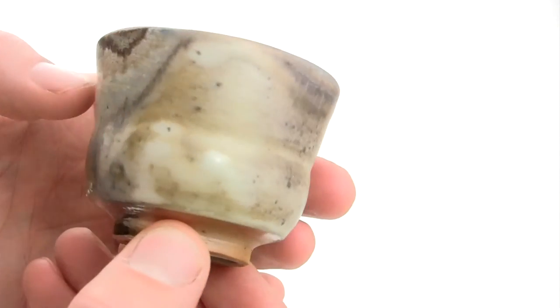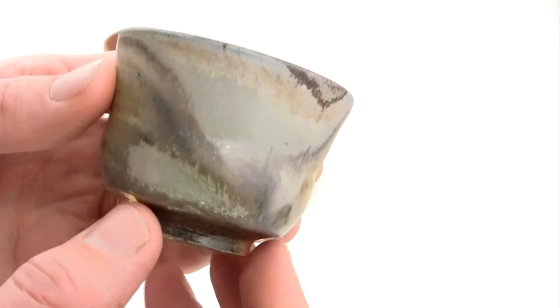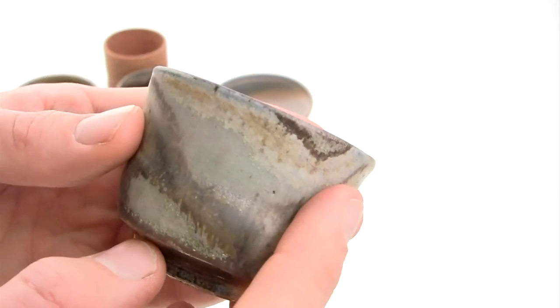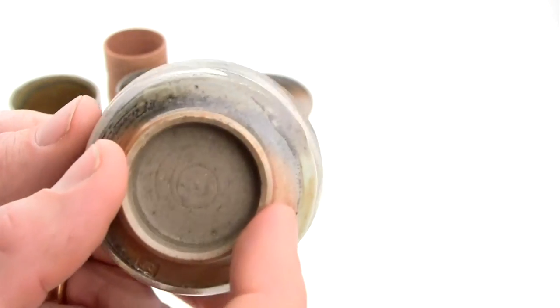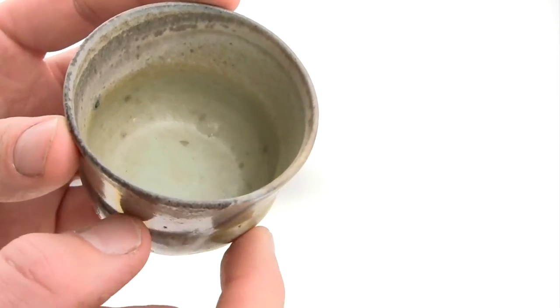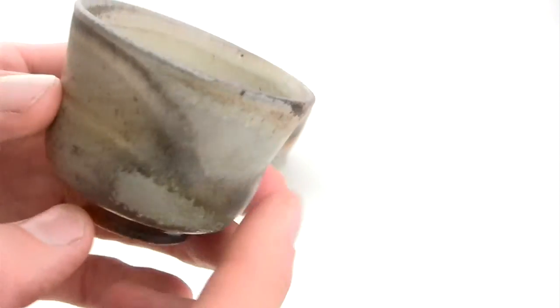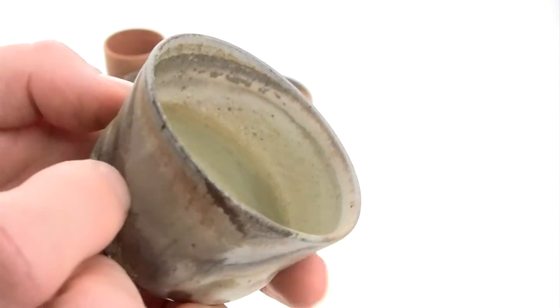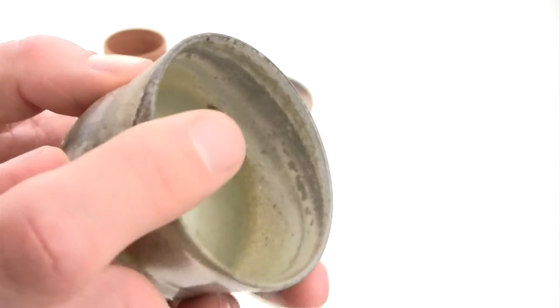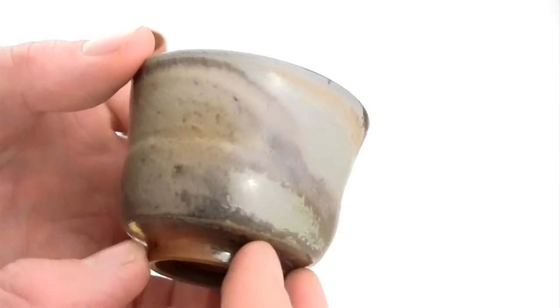On the fire side we have a higher temperature, a lot more flame, and specifically a lot more ash that sticks to the pot and reacts with the glaze — or actually the vitreous slip in this case — turning it into a glaze with the help of ash and starting to pour down the side. This is a fairly light stoneware clay with a vitreous slip on top. You can see how the flame has moved through the kiln, making a flowing pattern, turning the clay bluish and reaching down a little bit into the cup on the inside, but not all the way down.